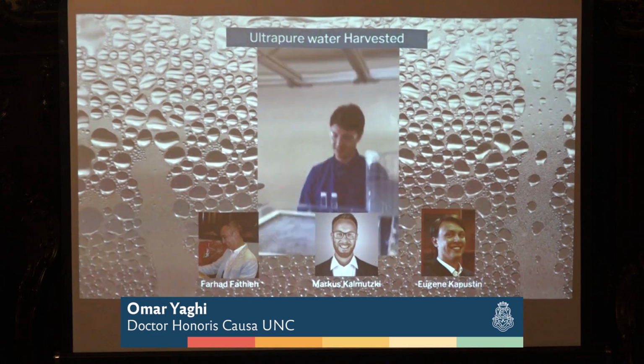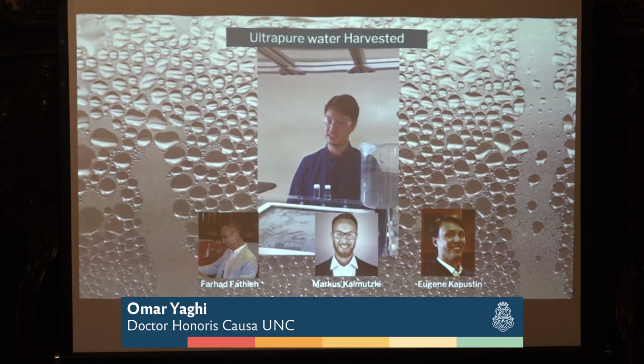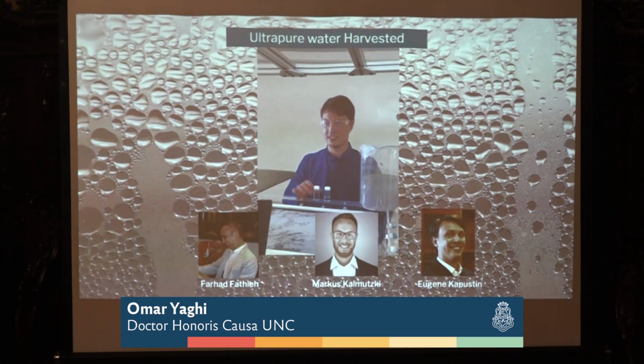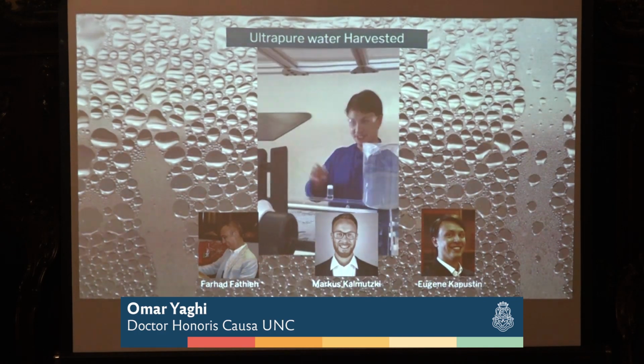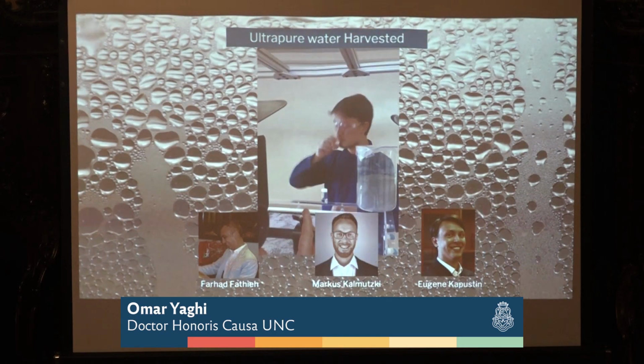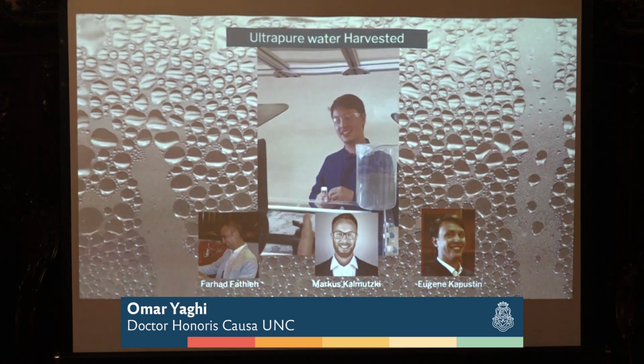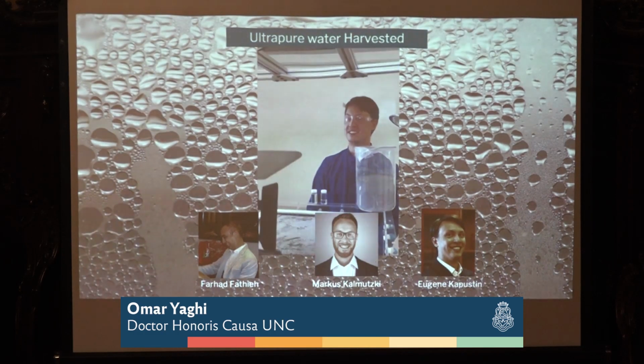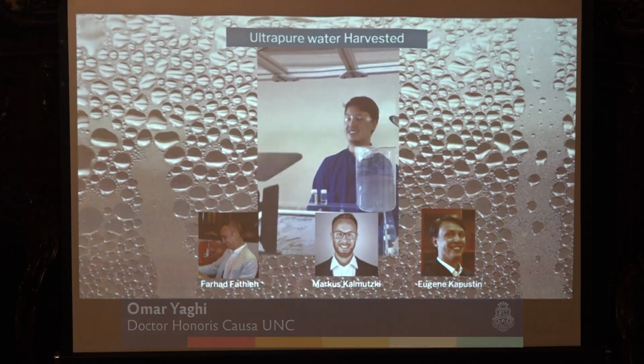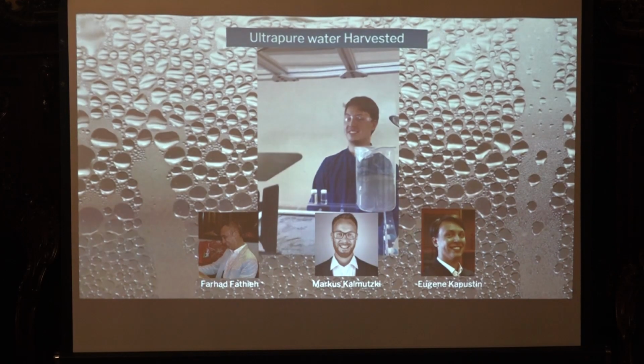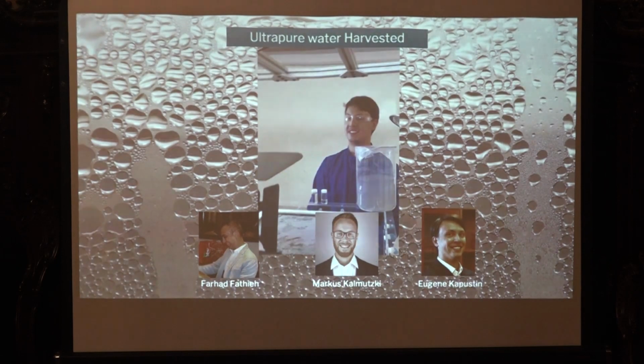And it's clean water. It's ultra clean. Cheers. Okay. It's distilled water, so it's not really as nice as Eugene is saying, but it's the cleanest water you'll ever get, okay? Because the pores themselves are a filter for water, and the water goes through several phase changes, and you have a very, very clean water. We tested it. It's all published.